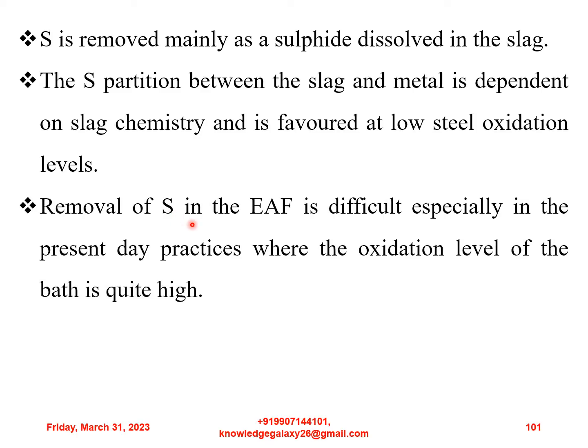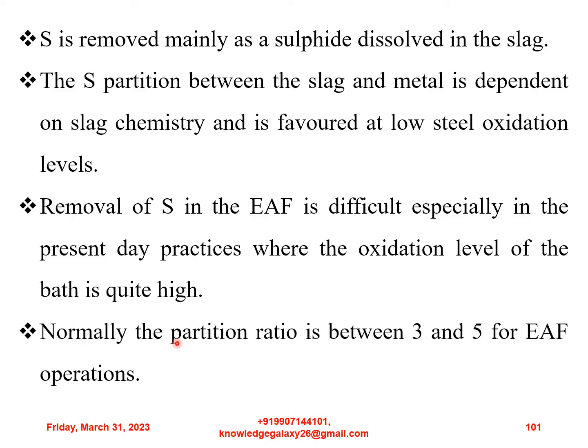Sulfur is removed mainly as a sulfide dissolved in the slag. The sulfur partition between the slag and metal is dependent on slag chemistry and is favored at low steel oxidation levels. Removal of sulfur in the electric arc furnace is difficult, especially in the present day practices where the oxidation level of the bath is quite high. Normally, the partition ratio is between 3 and 5 for electric arc furnace operations.